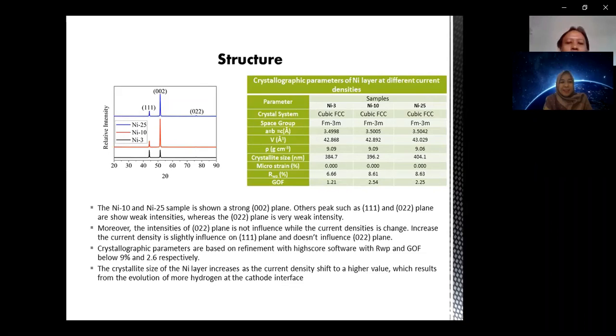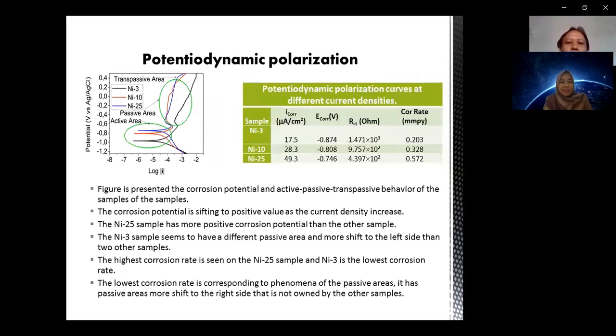The crystalline size of the nickel increases as the current density shifts to a higher value, which results from the evolution of more hydrogen at the cathode interface. In the potentiodynamic polarization figure, we can see the corrosion potential and the active, passive, transpassive behavior of the sample.